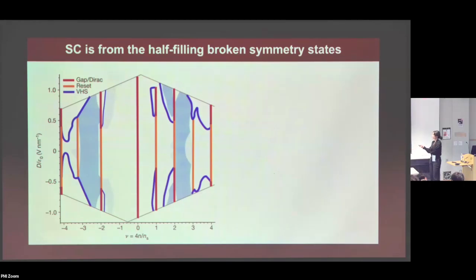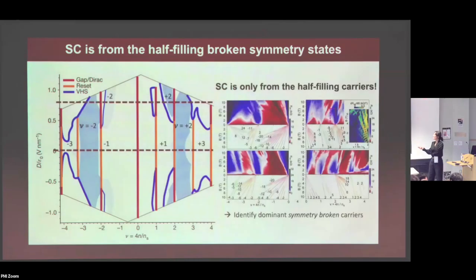So then what are these symmetry broken states? We can try to obtain what kind of symmetry broken carriers are dominant in all of these regions by measuring the quantum oscillations, which tells you the broken degeneracy of the system. You can measure these Landau bands across the entire map, in all these different lines in B. And then you can assign what kind of carrier or degeneracy is the most dominant in all of these regions in this entire phase space.